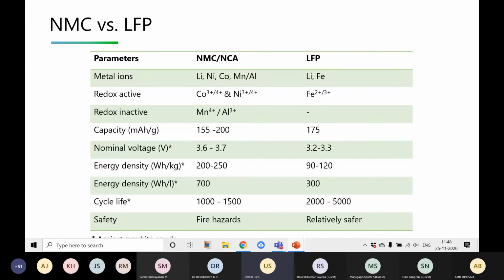So, but when we make the entire cell, let's compare it against graphite. Then in case of NMC, it will come as 3.6 to 3.7, and in case of LFP, the nominal voltage comes around 3.2 to 3.3. Energy density of NMC cell is more than 200, and it is crossing 250. In case of LFP, the energy density is quite less, almost half of it, 90 to 120. Energy density per liter, this volumetric energy density of NMC is around 700. In case of LFP, it is around 300.